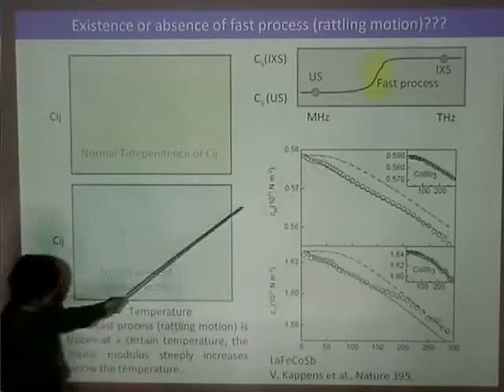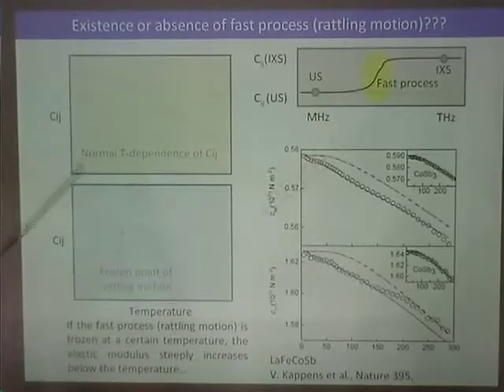So for example, CIJ means the elastic constant, CIJ versus temperature. Usually the elastic constants monotonically decrease like this figure, but when a faster process or relaxation exists, we can observe it in the temperature dependence of the elastic constants. So some modulus defects we can observe, like this figure.